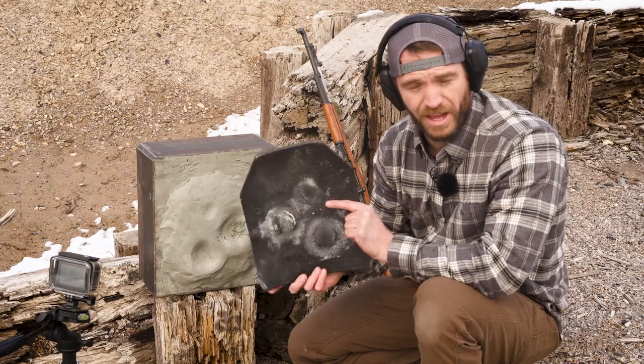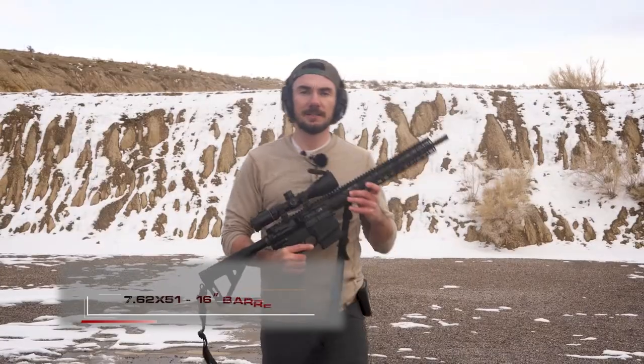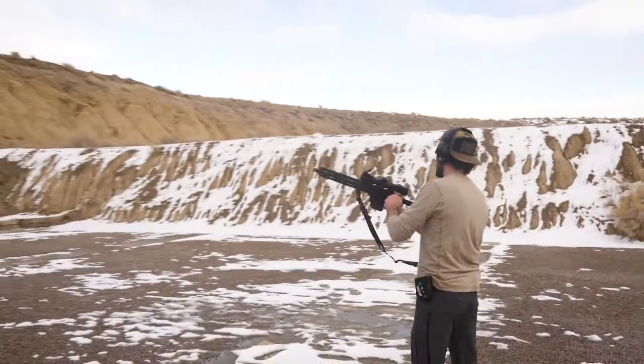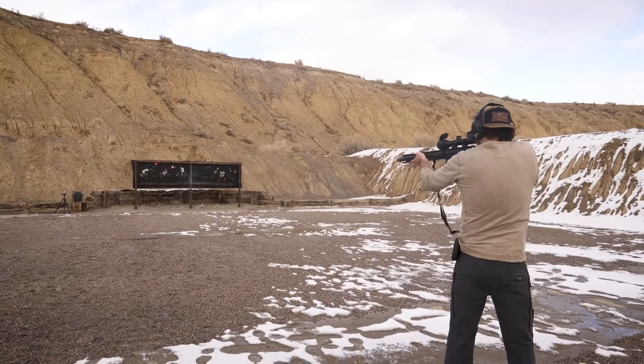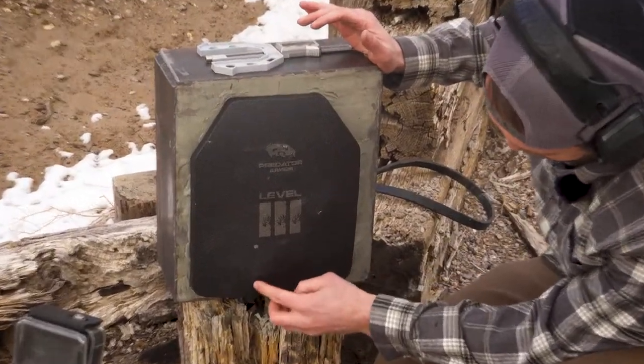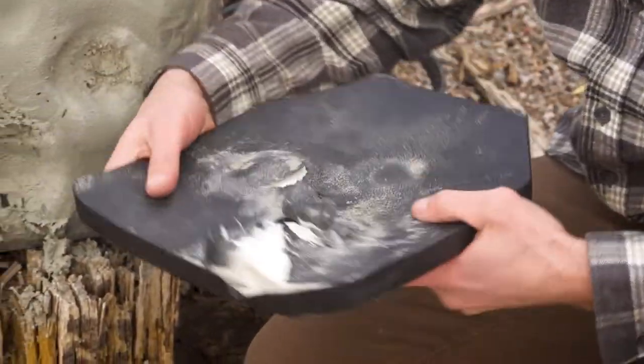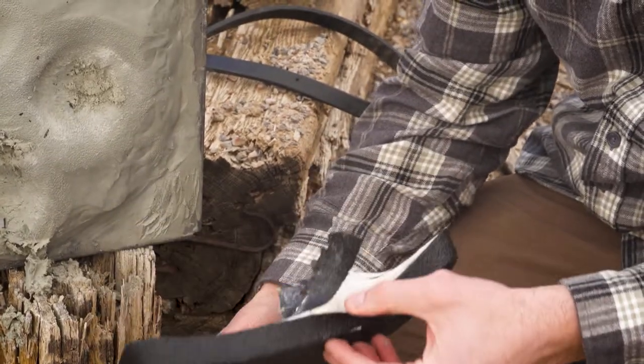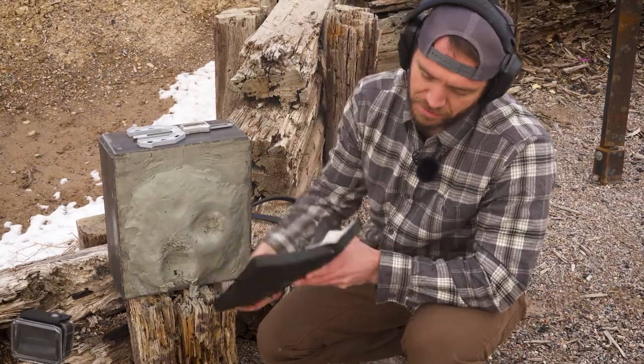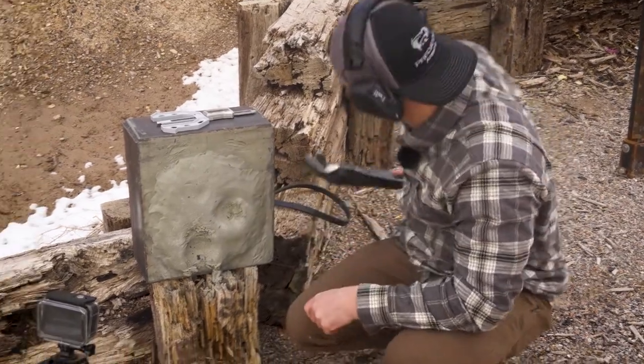Next up, we will hit it with the M80 ball round from the 7.62x51 — that is the standard for Level 3. So let's slap that up there and test it out. Here's the real test: 7.62x51 with M80 ball out of a 16 inch barrel. That shot you can see here, right under that 9mm hit. You can see it bulged and started to pull apart some of the covering on it. But you can see those layers are still intact. Even after five shots, it's barely starting to delaminate slightly — after five shots, so that's pretty awesome. Really held up.